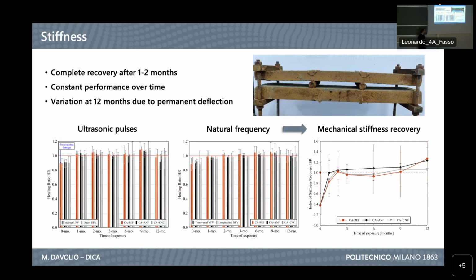As you can see, in most cases, after 1 month, we are already close to 100% of recovery, and the performance stays steady until 12 months, where we observed some slight reduction of the values. And also, with the index of stiffness recovery, which is then a mechanical measure, we observed the recovery from 80 to 100%, even after 1 month. And it progressed constantly at 100% for all the periods.